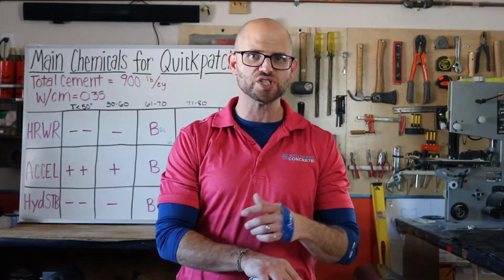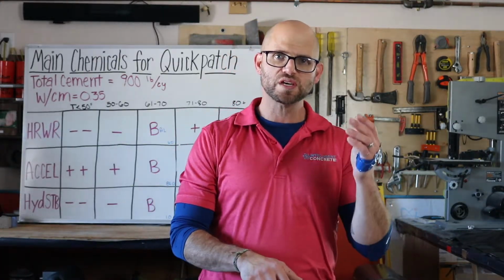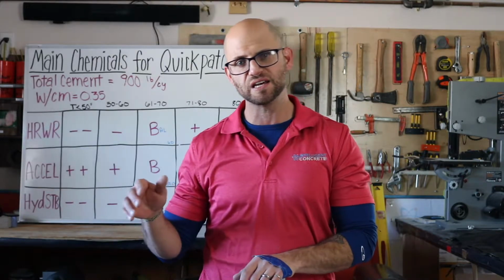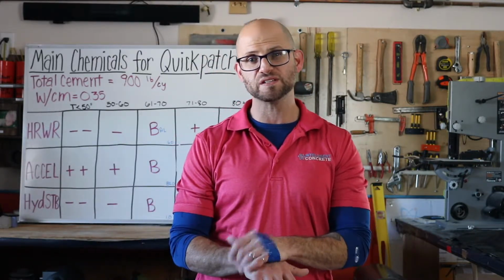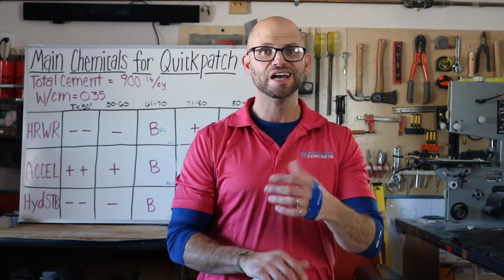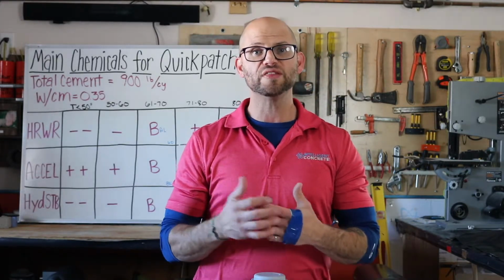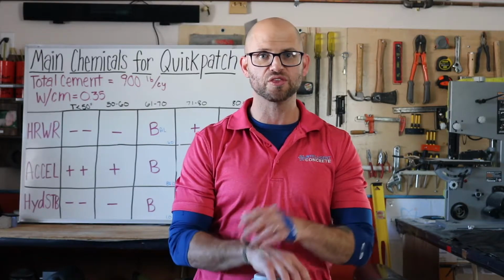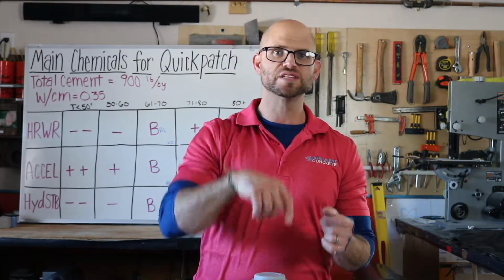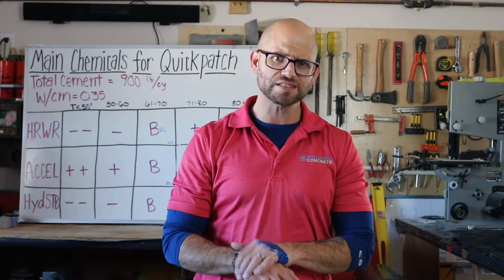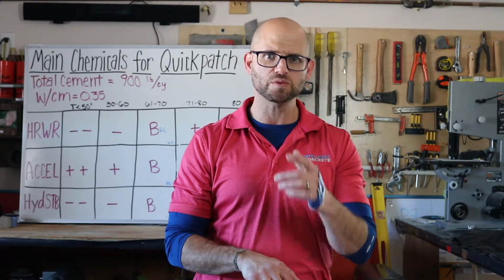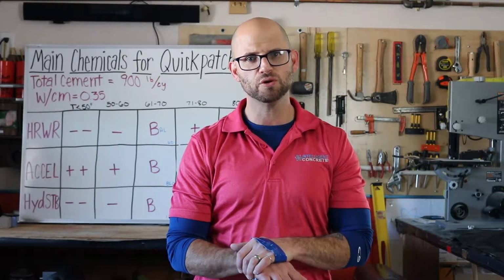What we're trying to achieve is somewhere between 1250 psi, really 2500 psi at 4 to 6 hours, and we're going to compare that to the reference. So you'll actually get to see what that chemistry does to enhance that thermokinetics and cement hydration to give us that early strength. So let's go ahead and take a look at that mix, and then we'll take a tour around the lab.